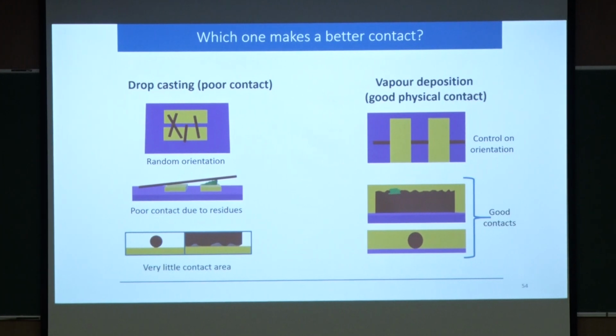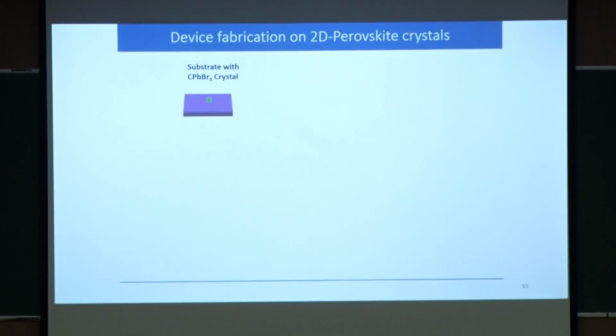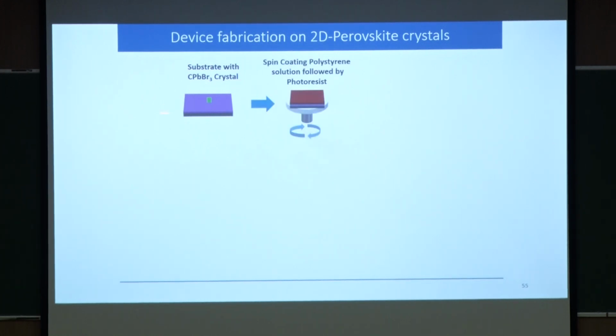And it will have a better contact as well. So, what we did, people are using some other techniques as well. We discovered a technique that is called sacrificial layer based technique. So, we have a CsPbBr3 crystal, and here we use polystyrene as a sacrificial material. You can use any material, just make sure that when you develop this material, it should not dissolve this water soluble thing. In this case, we can dissolve polystyrene in toluene, and toluene does not attack this one.